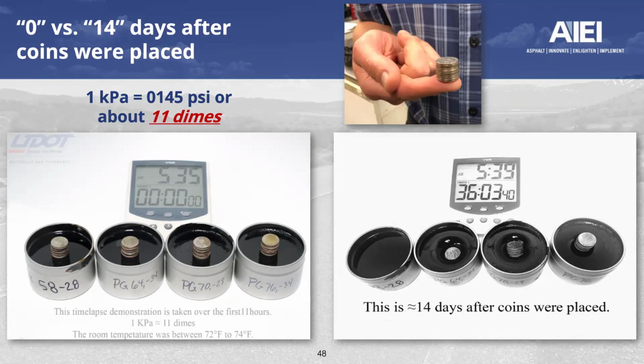You may be able to look real close and find a dimple on the surface of that 58, but essentially it swallowed it up. The typical polymer loadings, both of these are about a 3.5% or so polymer loading. We can see that the dimes over time, 14 days once more, at room temperature, slowly made their way in, but they're still visible. But very impressively, the 76-34 after 14 days, while it has deformed slightly, it is very minimal by comparison.